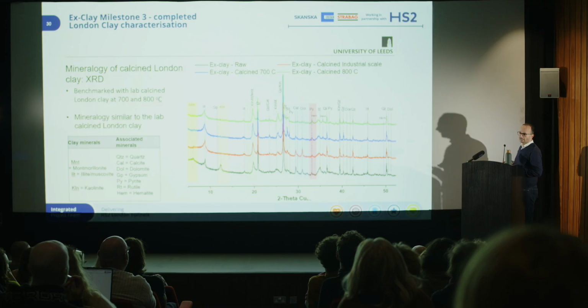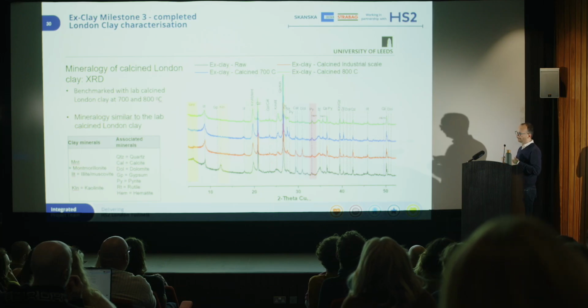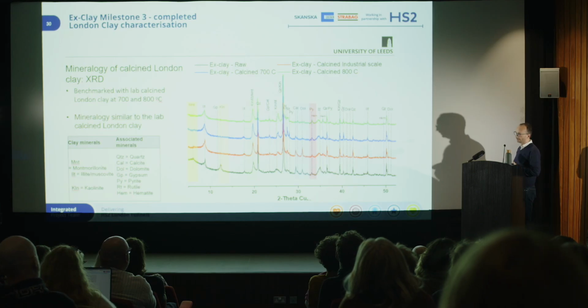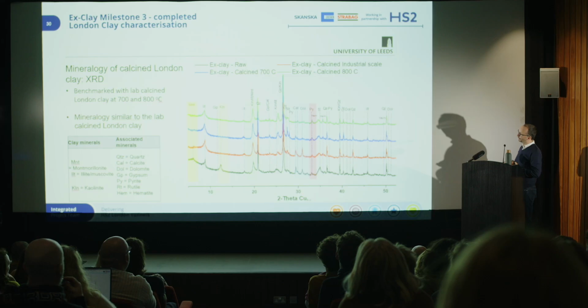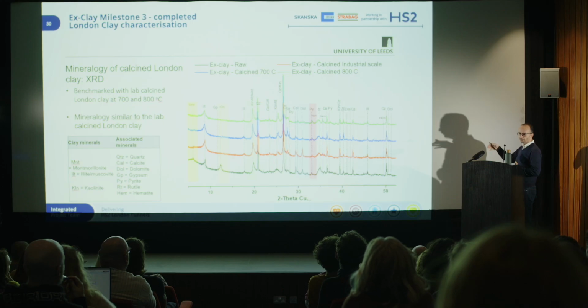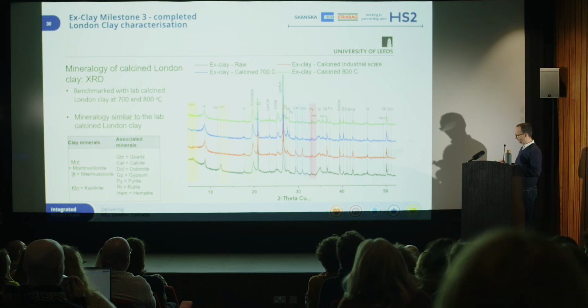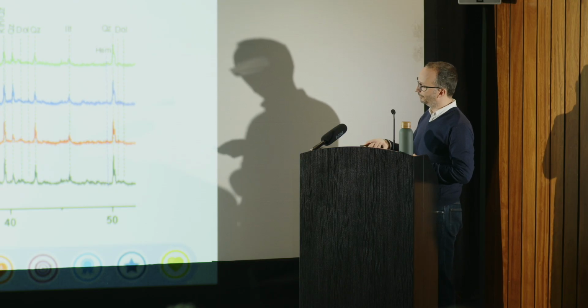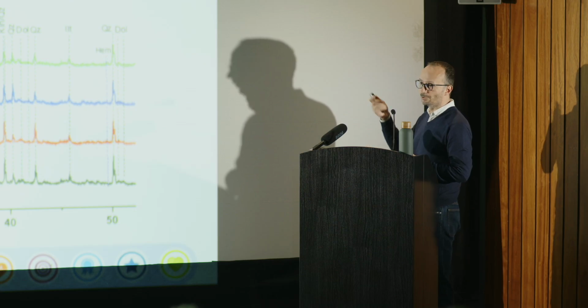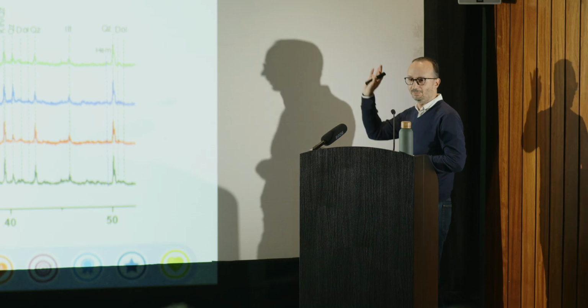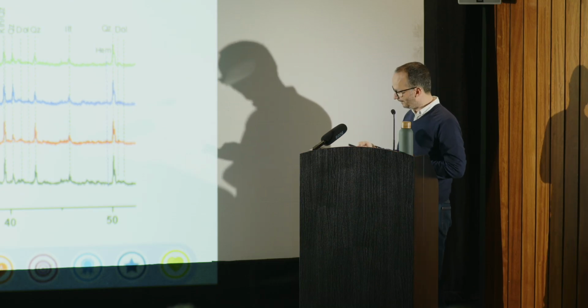Now in normal calcination processes, the limestone is heated and it gives us CO2 and it becomes clinker, it becomes different. What we saw here on the calcined industrial scale, we still have the peaks for this, which means that the facility that we used is not calcining the limestone in the clay, which means our CO2 emissions from calcination of the clay are even lower than what we would expect, even with that minor change. This was very interesting because we've never seen this before, but apparently this facility is achieving it and it's got a trademark process, how they do it. We don't know how they do it, basically.